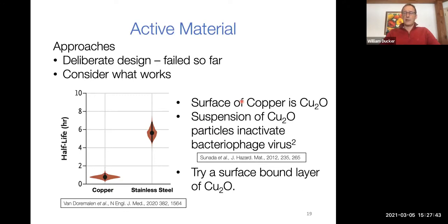I obviously knew that the inactivation was something to do with the surface. So I looked up my first year chemistry textbook from many years ago and learned that the surface of copper is cuprous oxide. And then I started researching cuprous oxide and found that somebody had put some particles of cuprous oxide into suspension. It's Japanese group Sunada, and they'd showed that it kills bacteriophage virus. So I thought, okay, let's try a surface bound layer as opposed to a suspension. We'll make a coating out of cuprous oxide.